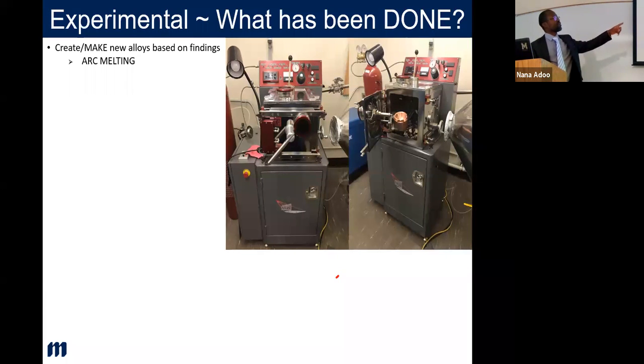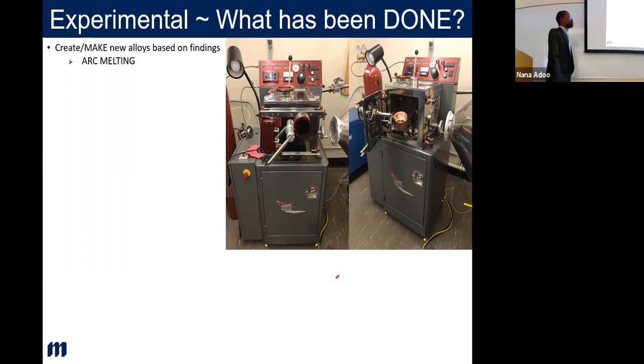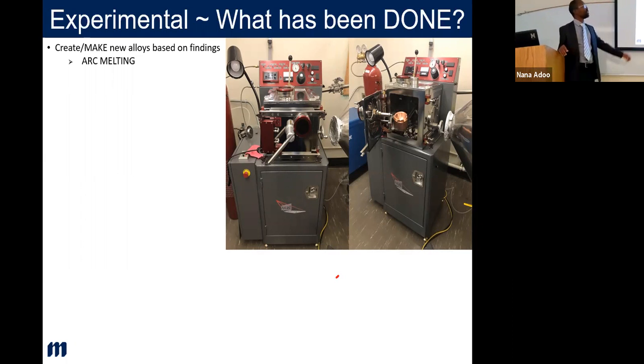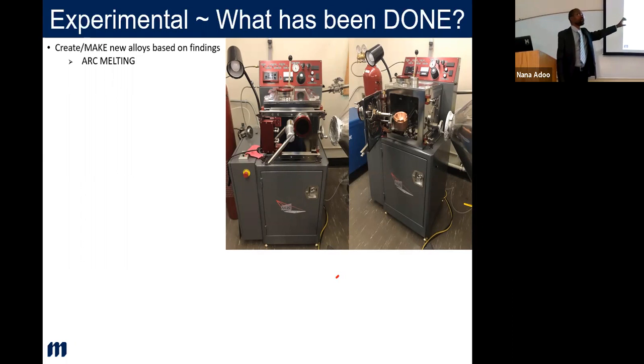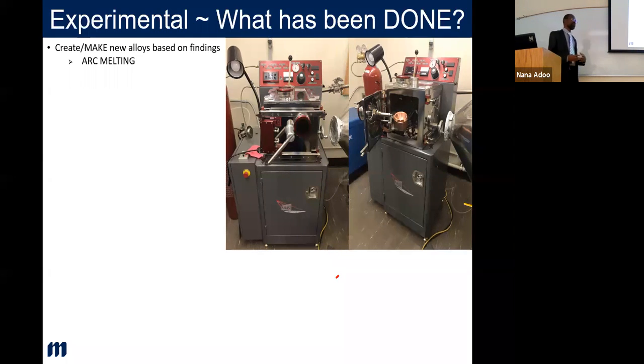This is a picture of the arc melting system that I used, a new system in the MES building. What's being shown here is the closed and then the open. I got 99.9% purity granules of iron, manganese, and gallium, based on calculations to get my E/A ratio in the bandwidth I showed, between 6.15 and 6.55. I measured everything, calculated, put them in the copper chamber, and then arc melted it.